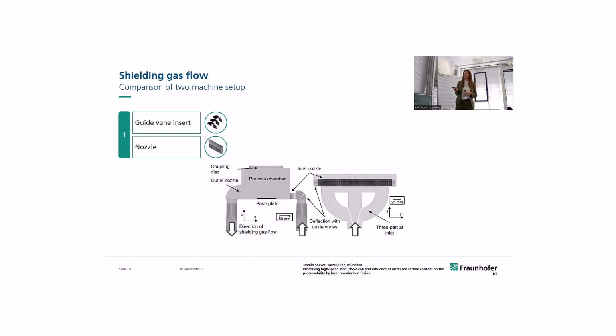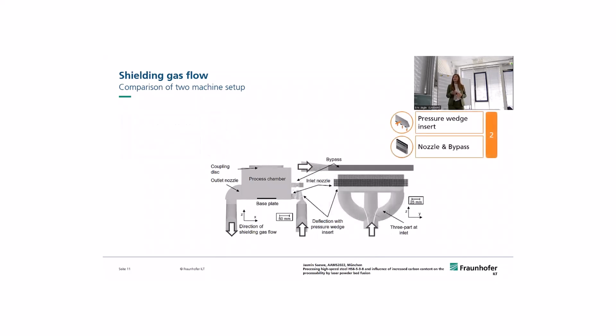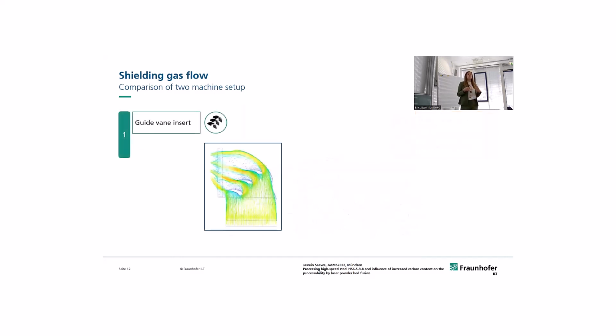As I mentioned, the 90 degrees is a little bit challenging when talking about the shielding gas flow, and I will go further into detail on why we use the second setup that you're seeing right now. It is a little bit different in how it moves the shielding gas through those 90 degrees. We have a pressure wedge, as we call it, and we also integrated a bypass, which supports the shielding gas flow as well. We used simulation for that, but I don't want to go deeper into detail here.